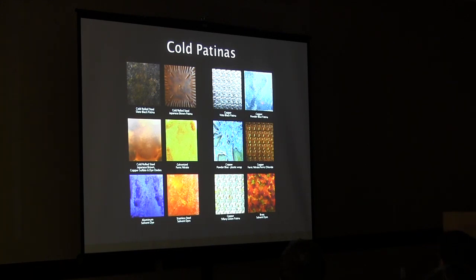This is copper, and I've got powder blue on here. You can have different types of blues. One blue would be accomplished by having ammonia in the chemical combination formula. But if it goes outdoors, the ammonia evaporates, and so you lose the blue and it goes to green. So powder blue has pigment in it. It has different blue pigments in it, so it's always going to stay blue outdoors. It just depends on what you're doing.